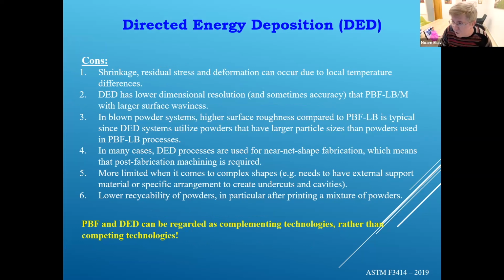If we look at the cons of the DED: shrinkage, residual stress, deformation, and lower dimensional resolution compared to powder bed fusion with laser. So they are more complementary technologies. That's how we should regard them, and not as competing technologies. Each one of them is more powerful for different applications. If you want quick manufacturing of large parts, near net shape, and you don't care about final polishing, for instance, then you would go with DED. Or if you want multi-materials. On the other hand, if you need very fine cellular structures, cages for orthopedics or stents and so on, you will go with powder bed fusion.